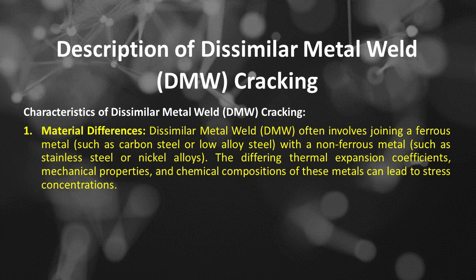Number 1 is material differences. Dissimilar metal weld often involves joining a ferrous metal, such as carbon steel or low alloy steel, with a non-ferrous metal, such as stainless steel or nickel alloys. The differing thermal expansion coefficients, mechanical properties, and chemical compositions of these metals can lead to stress concentrations.